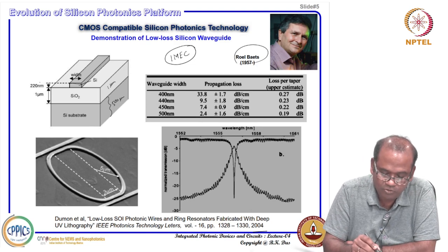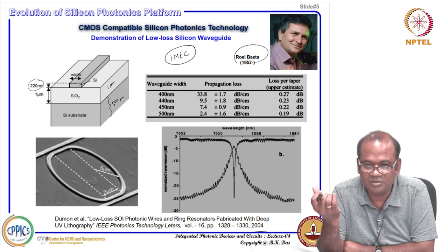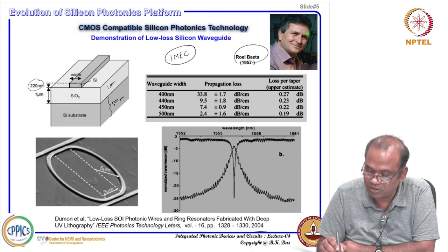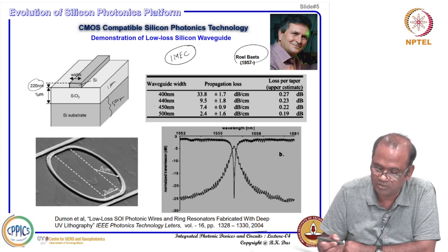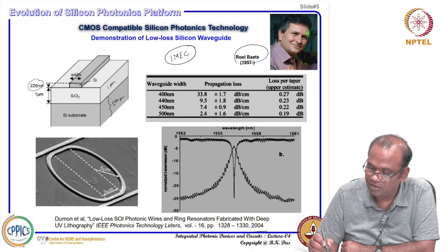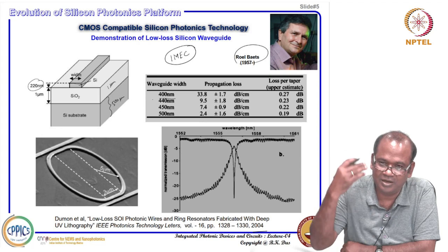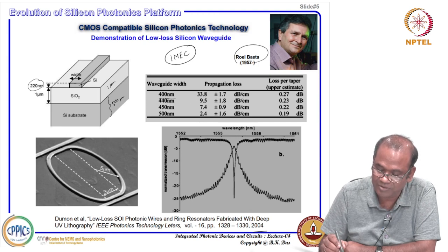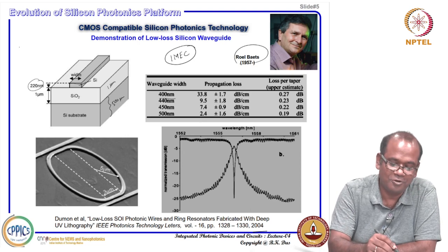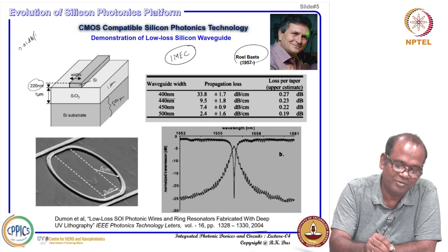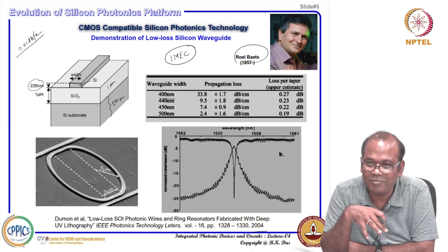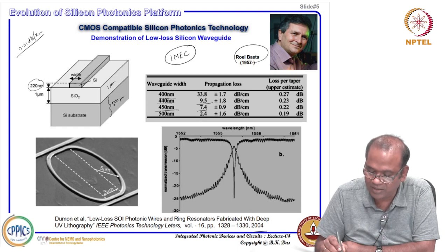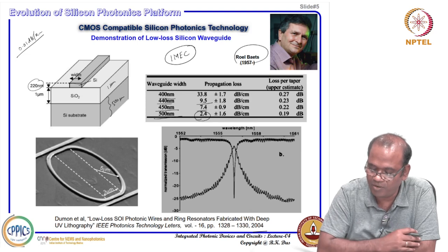They showed that, depending on the width — since the 220 nm wafer thickness is fixed when purchased — controlling width W allows fabrication of different waveguides. The loss per centimeter was measured: at 400 nm width, about 33–34 dB/cm for this early primitive SOI waveguide structure. Increasing width reduces loss: about 10 dB/cm, then 7.4 dB/cm, and at 500 nm width dramatically low — about 2.4 dB/cm.